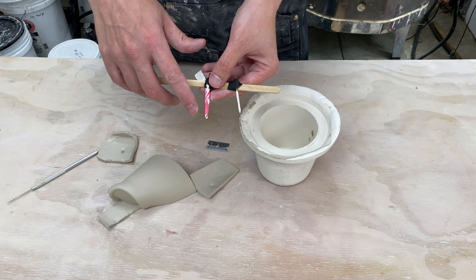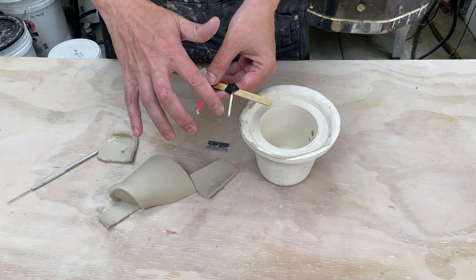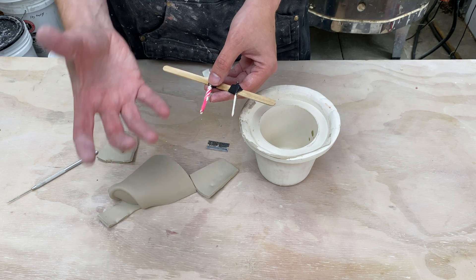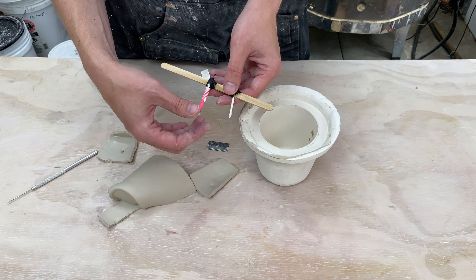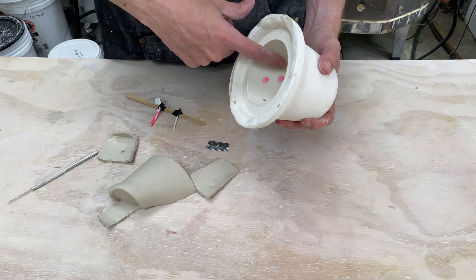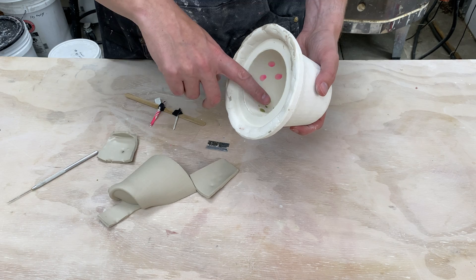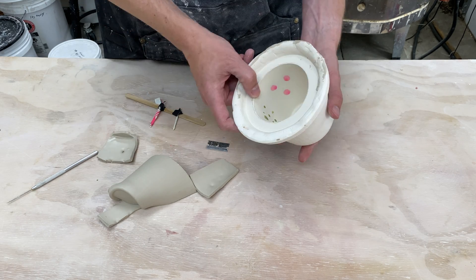And of course now I have wax on the inside of this mold, which would not come out. That's okay — if it actually worked, I wouldn't mind keeping the wax in there. But this didn't quite have the desired effect. So yes, the wax does prevent the water in the slip from being absorbed directly, but I think it kind of goes around the outside. This test here shows that the wax does actually repel the slip, so I was wrong about the hydrophobic nature. The surface tension of the slip was enough to grab onto the nail, but the wax resisted that. So the wax is indeed repelling the water in the slip, but the properties of the slip itself are what's forming the dome over the top of this. So that was an interesting test, and I was both right and wrong.